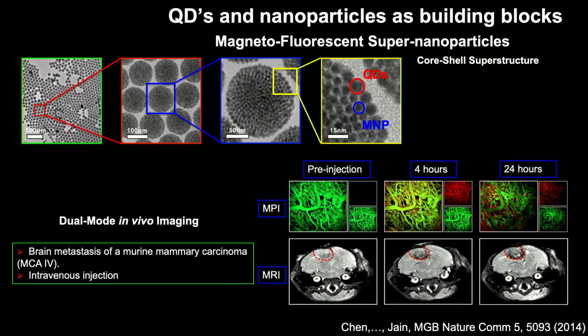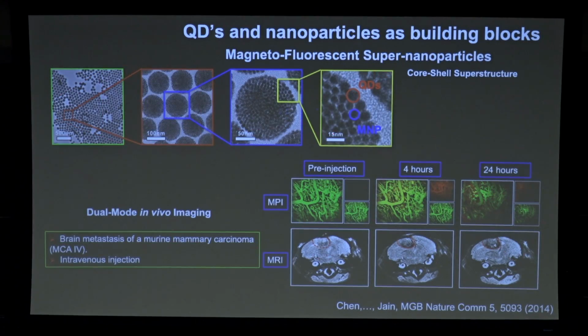It turns out that the quantum dots are on the outside of these large balls and the magnetic particles on the inside. We were doing biology experiments with quantum dots at the time, so we decided to see if we could use this as a dual imaging agent. So this is a mouse model. This is a GFP, green fluorescent protein, mouse model. So this is the GFP imaging here. We inject these particles, and this is a mammary carcinoma in this model, and you can see the particles basically get trapped inside the tumor through this enhanced permeation effect. And at the same time, you can read it in the MRI, the increase of the concentration of these particles because of the magnetic properties.